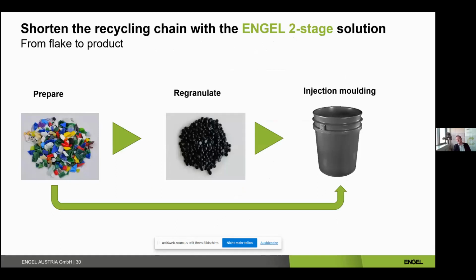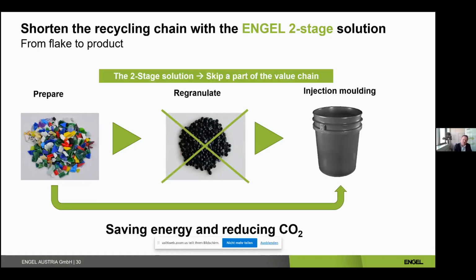Okay, and if you're using this technology and running flakes directly into the injection molding process, we save the regranulation process, which means all the energy that is needed for melting the material and cooling down. So let's say roughly 400 watt-hours per kilogram can be saved if running flakes directly in the injection molding machine. And therefore, it's also a reduction of the carbon footprint of the product. And this is